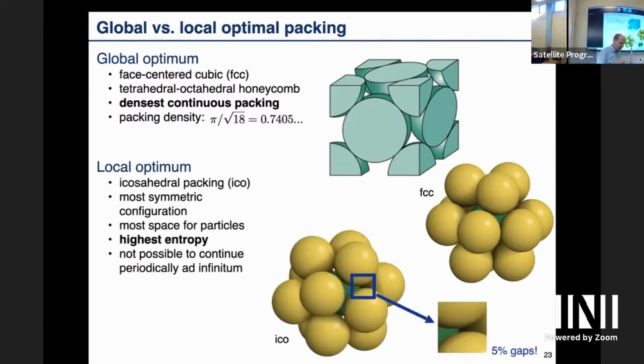On the other hand, if you look at the local optimum, then what is better than the FCC packing is an icosahedral packing. And it's better from the perspective of entropy, because it's a very small rearrangement of the particles, since it still has coordination number 12. You can introduce gaps by symmetrizing the structure from cubic symmetry to icosahedral symmetry. And these gaps, 5% distance between the particles, 5% in terms of the radius, add entropy to the system and make this actually entropically more stable.